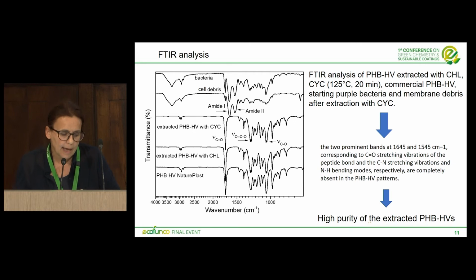In this slide you can see the FTIR spectra of the starting bacterium, the cell debris, compared to the FTIR spectra of the extracted PHB-HV using cyclohexanone, chloroform, and also the FTIR spectra of the commercial PHB-HV by Naturplast. And as you can see, the two typical bands corresponding to the carbon-oxygen stretch vibrations of the peptide bond, and the carbon-nitrogen stretch vibrations and nitrogen-hydrogen bending modes are absent in the PHB-HV spectrum, PHB extracted by chloroform and by cyclohexanone. And this confirms the high purity of the extracted PHB-HV.